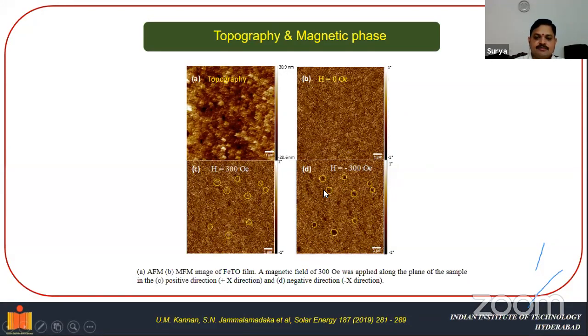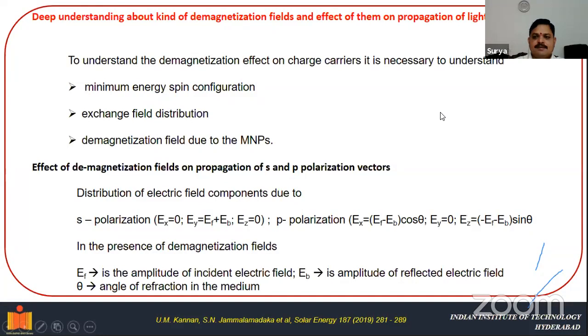Okay. From this, we can say that the nanoparticles exist in the device. These nanoparticles are generating demagnetization fields. These demagnetization fields are improving the efficiencies of the solar cell device. Okay. So on top of that, we have proved that there exists a magnetic nanoparticle in our device, and the demagnetization fields due to the stray fields of the nanoparticles improved the efficiencies of the solar cells. Okay. We also have done some simulations.